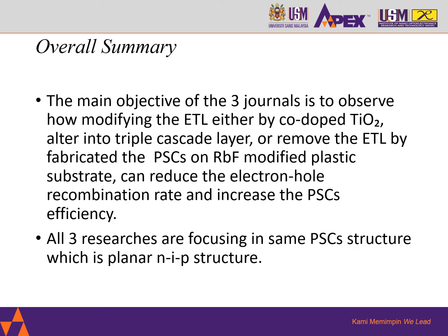As mentioned, the main objective of the 3 journals is to observe how modifying the ETLs, either by co-doping the TiO2, altering the ETL into a triple cascade layer, or even removing the ETL by fabricating the PSC on an RbF modified plastic substrate, can reduce the electron-hole recombination rate and hence increase the PSC efficiency. All 3 researchers are focusing on the same PSC structure, which is the planar NIP structure as I showed in the previous slide.